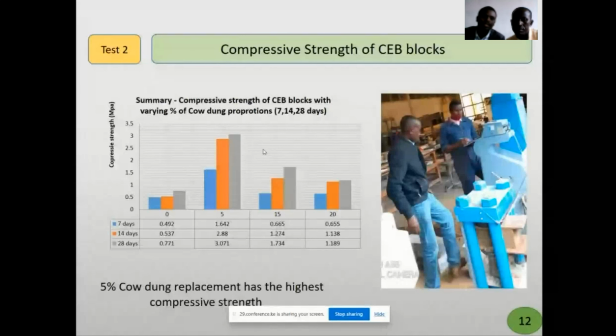On the compressive strength, generally we find that 5% cow dung replacement in these CEB blocks gives the highest compressive strength, and we can see that we have achieved 3.071 megapascals as the compressive strength. From the research, we have an average of 2 to 3 megapascal compressive strength in these compressed earth blocks. So we can say that we've achieved a substantial compressive strength from the 5% replacement of cow dung powder.